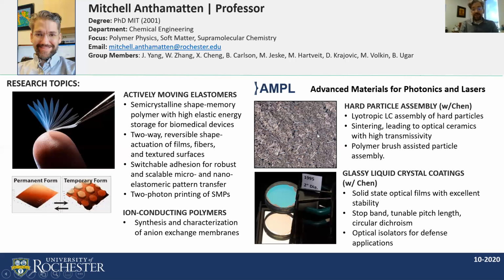What we're interested in is making nanorods, and we've done this. Wenxi Zhang and Xinchuan Cheng are working on making nanorods that can undergo self-assembly in a solvent. That's called lyotropic self-assembly. And then once we've assembled them, we can remove the solvents and sinter them together. And with sintering, we found that we're able to retain some of the particle alignment. And this leads to anisotropy in a solid state material. And since they're nanoscale particles, they don't scatter light. So we can have highly transmissive anisotropic materials that are birefringent. So the application could be optical wave plates, for example. And we're working also to use polymer brushes to assist that particle assembly.